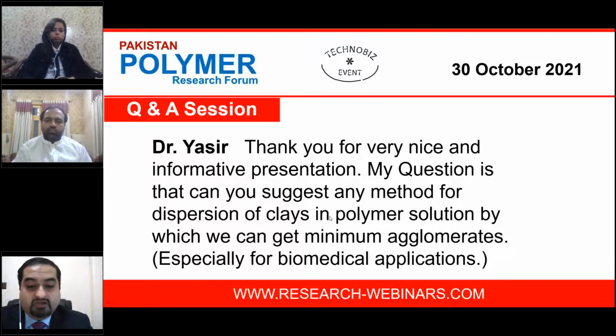Yeah, for biomedical applications, once again, in order to enhance the properties, you have to look for two of the techniques. You do need to keep in mind that I'm not in favor of chemical modification, especially once we are talking about biomedical or packaging applications. Ultrasonication can give you very good options in terms of eliminating the agglomerates. But then, once you are trying to make sure how those polymer solutions are being dried out, that becomes a really important criterion. If you are just going to leave them in a drying oven, then all of the agglomerates that you have broken down with the help of sonication or even by exposure to microwaves will try to reassemble.